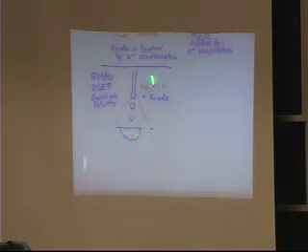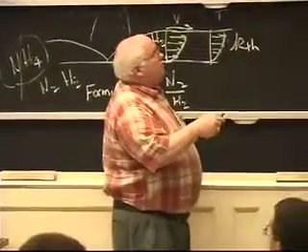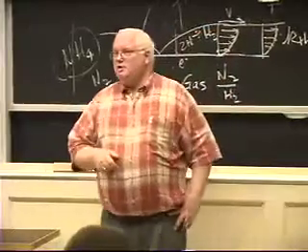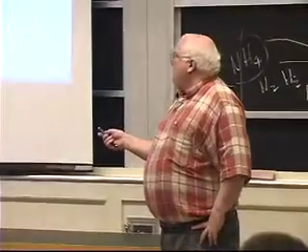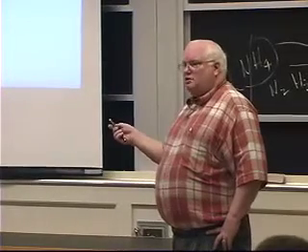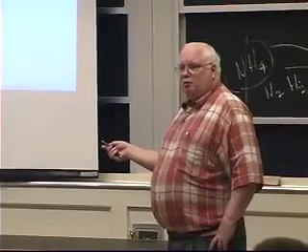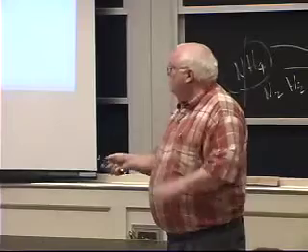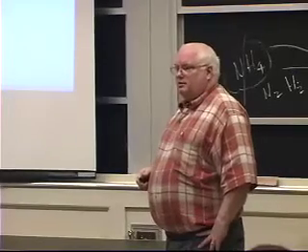And the anode becomes the wire, and the cathode is the workpiece. So for iron, aluminum, nickel, we typically will have this as the anode. And why is that? Because that's what I'm trying to melt. I've got a groove that I'm going to try to fill up with big blobs of weld metal, okay, weld beads. And I'm going to try to improve the efficiency of my process by putting my 2/3 of the heat into the wire, which is what I want to melt. And I don't really need to melt much of the base plate. I just need to fuse it so that I get good fusion inside that little V groove.